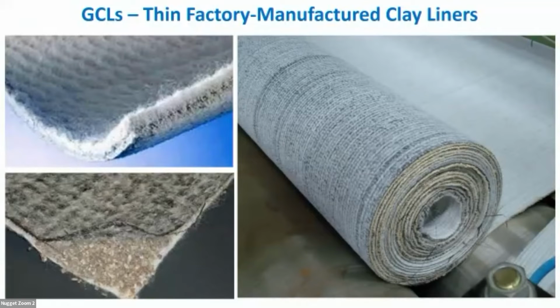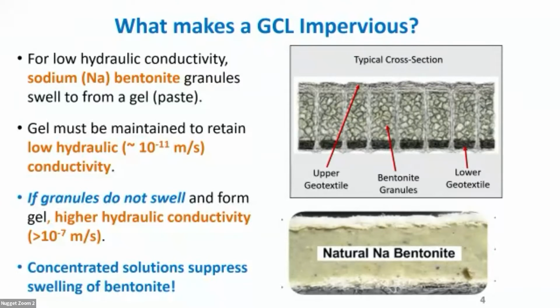You can see the dry granular bentonite on the interior, and they'll come in a roll, and we can roll this out at the site. Very quick construction, overlap it. It tends to hydrate from moisture moving up from the subgrade, potentially creating a very impermeable material. For these materials to work, though, that granular bentonite, which looks like sand, it doesn't look very impermeable in itself, it has to transform itself. And that's really where the geochemistry comes in.